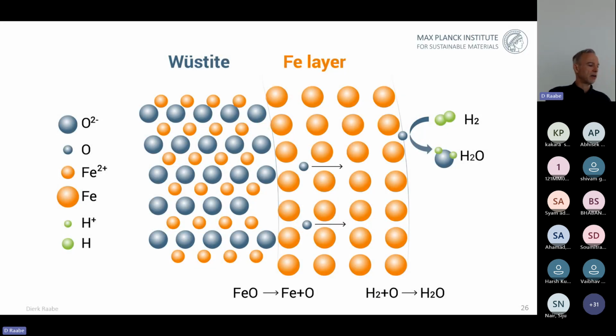And when we jump back into this atomistic picture that I have tried to share before, then we can render this schematic by showing the wüstite on the left-hand side, the interface to the iron layer above it, and the necessity to have the oxygen atoms here, oxygen 2- anions, shown here in blue, stripping off the 2 electrons so that as an oxygen atom it can diffuse outbound to form the water at the next nearest surface. And the next nearest surface is not necessarily the free percolating surface, but it can be also one of these inner pores that I've shown to you before. Because the oxygen is not very smart. The oxygen is just following a gradient in the local chemical potential that points at any free surface, be it an inner or an outer one.